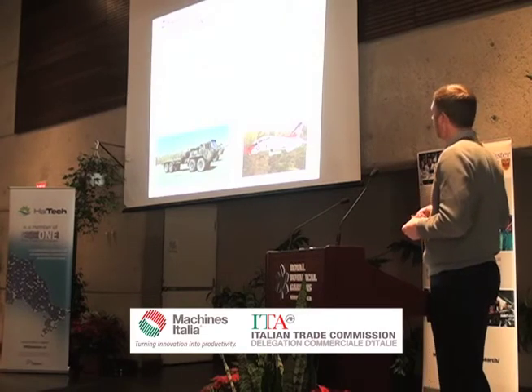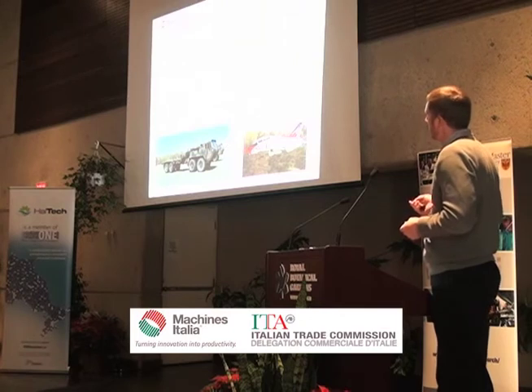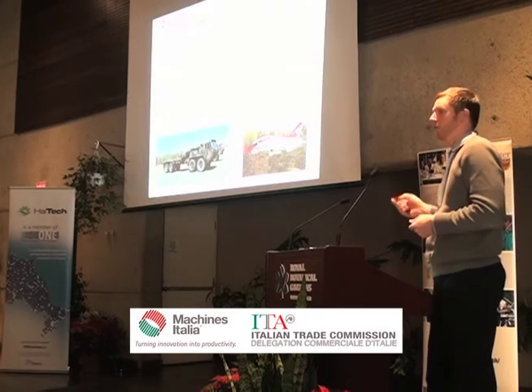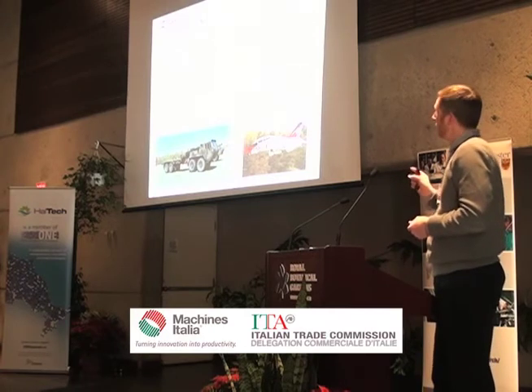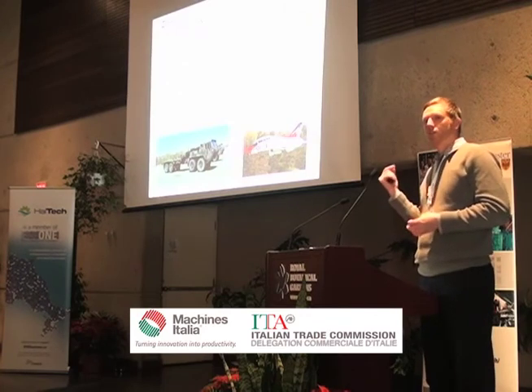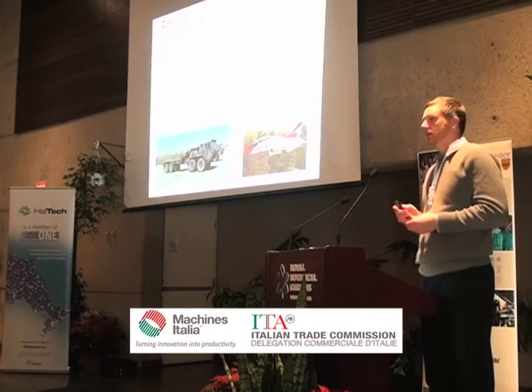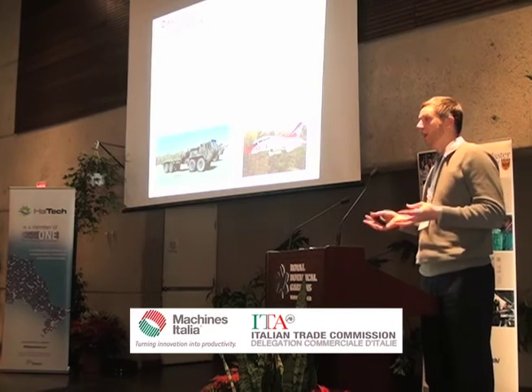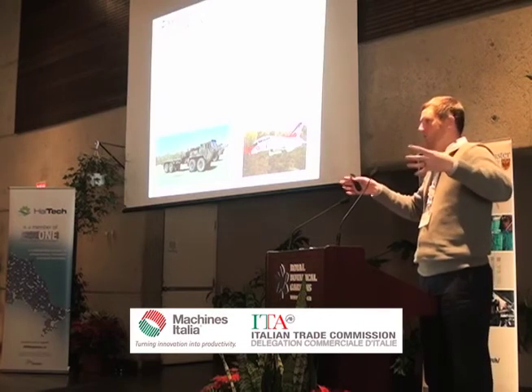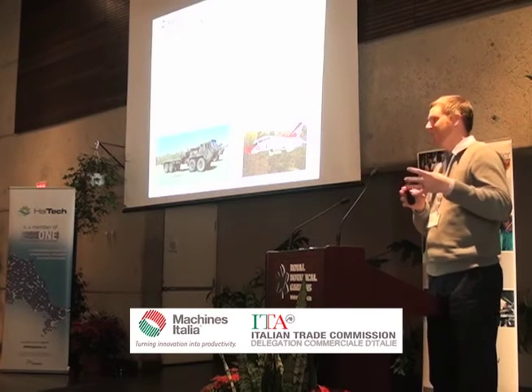This is maybe 8 years later after the original work that we did. So we developed this Nanovate Co-P electroplating process, and essentially it's a drop-in for hard chrome. Except that when you compare the two processes, Nanovate Co-P and hard chrome, the Nanovate Co-P process is much more efficient. It allows you to process a larger number of parts with the same tank than you would for your hard chrome tank. So essentially, take 4 tanks of hard chrome you might need, you can condense that down to 1 because the plating rate is just that much faster.